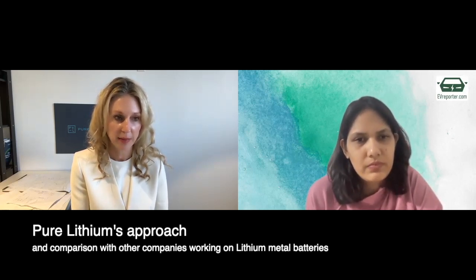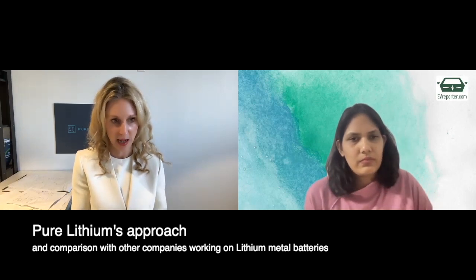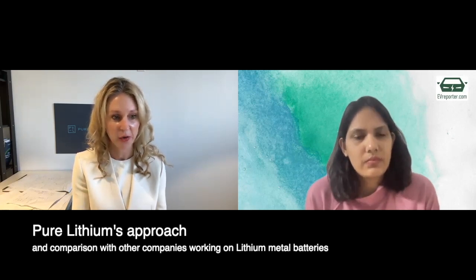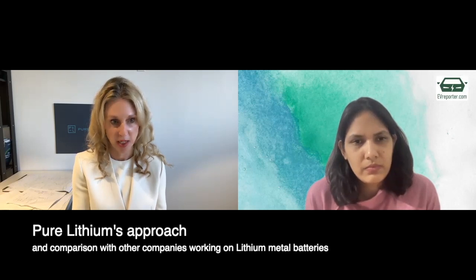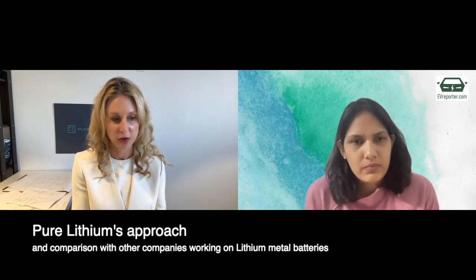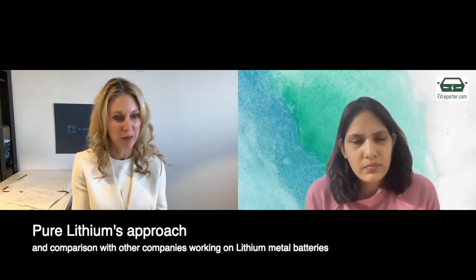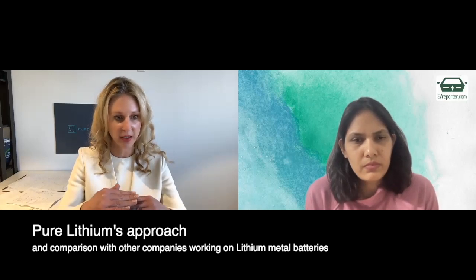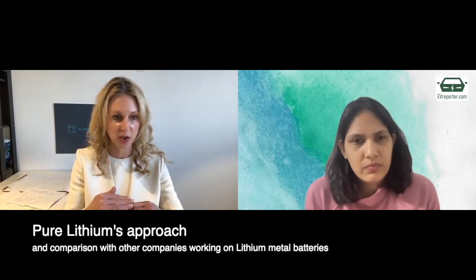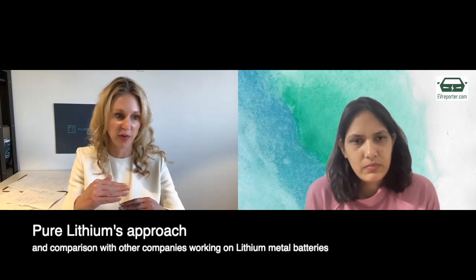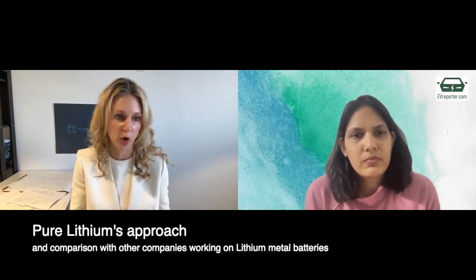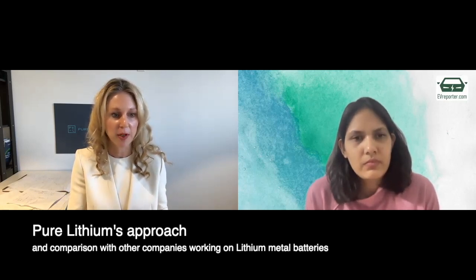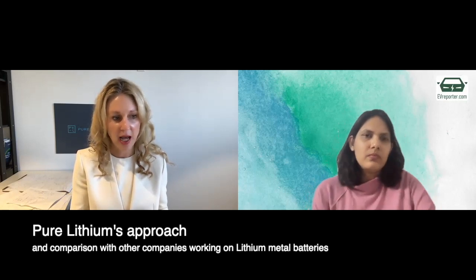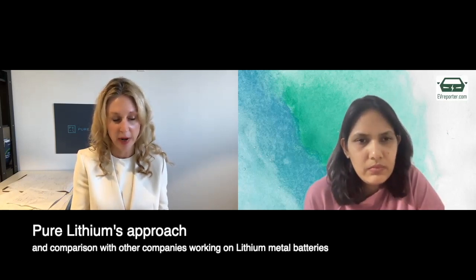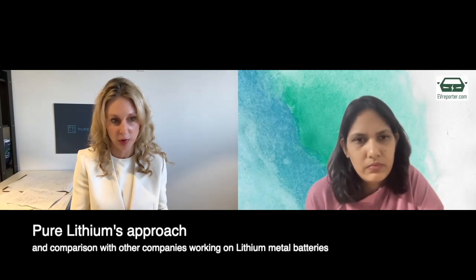What we do at Pure Lithium is two things. We make our own lithium, and we do this through electrodeposition. So instead of extrusion, which is think of a Play-Doh machine almost, where you have to smush the lithium, we grow it from the surface of a piece of copper. So we can make a 5-micron thin film very easily. We just stop the current. It's a function of current density and time. So we build our own anode in-house. We filed a lot of intellectual property around vertically integrating our own lithium metal anode production.